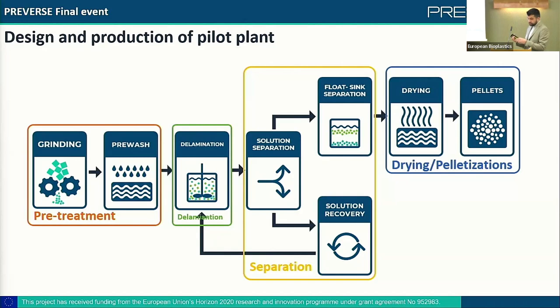multilayer are made of polymers with different density, such as PA, PET, it is possible to separate them using a float-sink separation. And after this, the material is dried and pelletized. The drying is necessary to remove the water remaining in the material after the washing. After this, the material is recycled in an extruder to obtain the pellets. Now I want to show a small video in which we see the use of the pilot plant for the material separation.